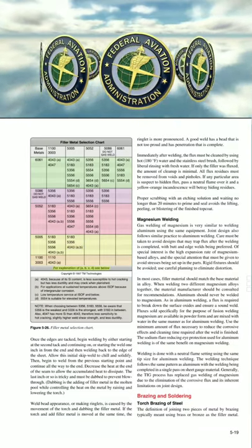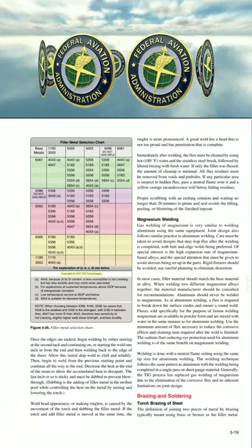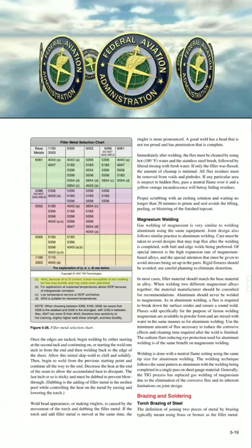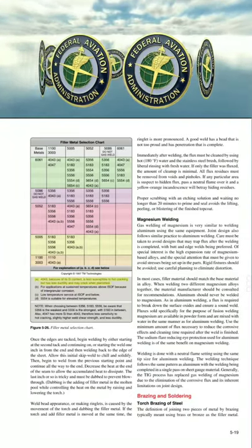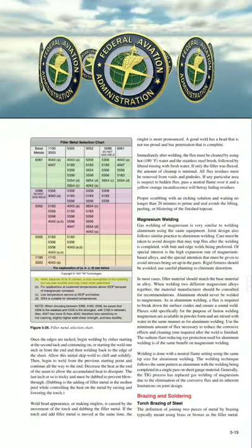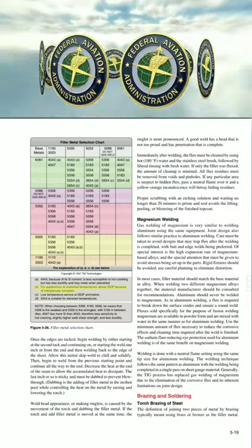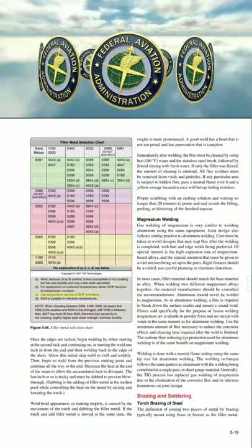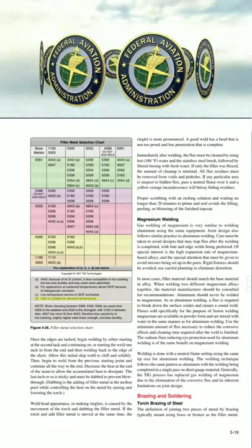For explanation of A, B, C, D, see below. Copyright 1997 TM Technologies. A: 4043, because of its high silicon content, is less susceptible to hot cracking, but has less ductility and may crack when planished. B: for applications at sustained temperatures above 150 degrees, because of intergranular corrosion. C: low temperature service at 150 degrees and below. D: 5554 is suitable for elevated temperatures.